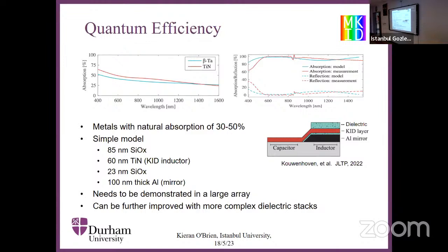In terms of quantum efficiency, typically in the early arrays, all the current arrays that we have, the quantum efficiency is relatively low. It's in this 30 to 50% range, which if you're more used to CCDs is not great. If you're more used to other detectors, it probably isn't too bad. But there are efforts going on, and this summarizes some of the efforts ongoing to increase that